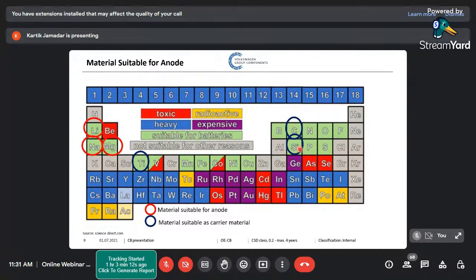But as you can imagine, if your anode is holding more and more lithium, it will also expand, and the expansion will be more like 300%. Your cell will expand by 300% if you have silicon because it can hold so much lithium, compared to around 18 to 20% in the carbon. And now the main problem is how to control that expansion. So there is a lot of research going on on how to give a uniform compression pad so that the cell does not expand non-uniformly and so on. And that's why we are not putting 100% silicon. We basically have around 10 to 50% silicon in our graphite. The rest is still graphite.